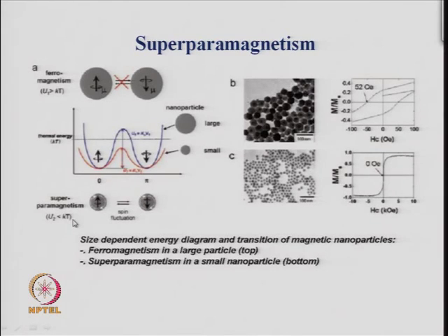So, what will it look like when you plot the magnetization? How will the hysteresis loop look? So, for a large particle, where you plot magnetization on the y axis and the applied magnetic field in Oersted on the x axis, you see that there is a loop. Although the loop is not closed here, if you go to higher fields, this loop may close, but you can see that there is an area under the curve when you plot magnetization versus magnetic field. This is for large particles.